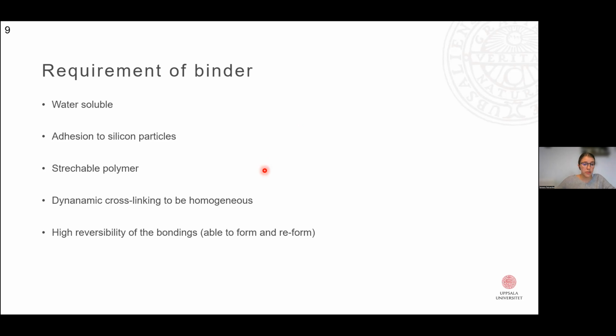To cope with a mechanical stretch, we need a stretchable polymer that is able to follow these volume expansions that we have. So it needs to be quite stretchable. It is also important that this dynamic cross-linking is quite homogeneously spread through the polymer chains to help the silicon in the same way throughout the particle, so it's even. And of course, we need a high reversibility of the bondings so that we are able to form and reform them many times throughout the cycling. So I will show some examples of binders now, and first functionality is based on hydrogen bonds, and thereafter we move on to the dynamic covalent bonds.